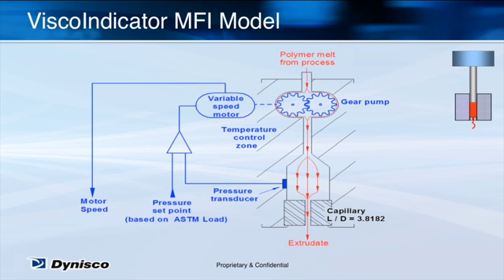So by measuring the gear pump speed required to control pressure at the ASTM set point and knowing the pump flow rate, the ViscoIndicator is able to calculate MFR directly as a function of the pump RPM, given that the melt density is known. If you don't know the melt density of your polymer, you can easily measure it using a standard method on a melt flow indexer. This is how a ViscoIndicator duplicates the test result from a melt flow indexer right at the extruder without needing a technician.